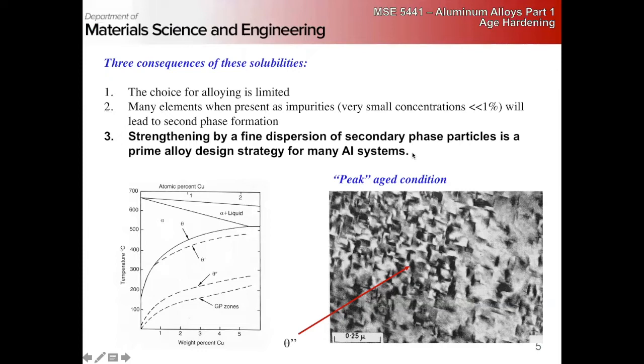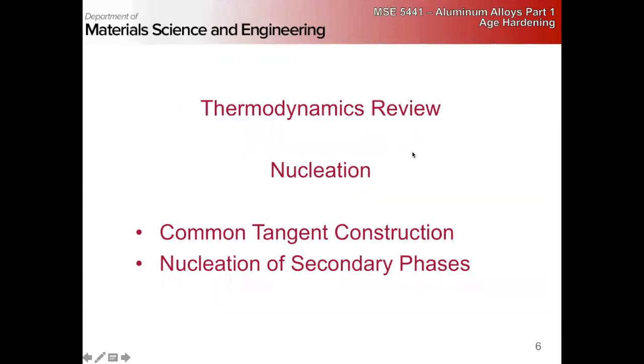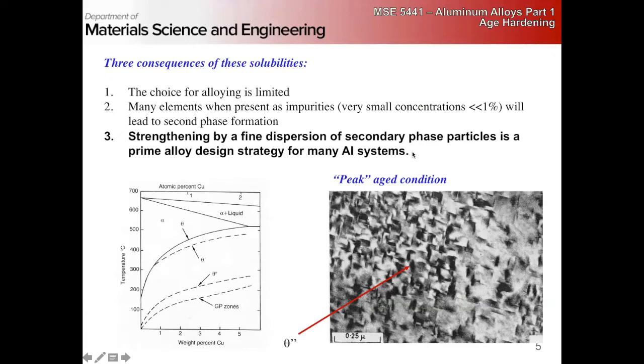But it also means that we can make advantage of this secondary phase formation by developing a fine dispersion of these secondary phase particles, and that's going to be a prime alloy design strategy for many aluminum systems. And here we can see a very fine dispersion of theta double prime particles. This is this metastable phase here that we'll talk about in great detail later in an aluminum copper alloy system.